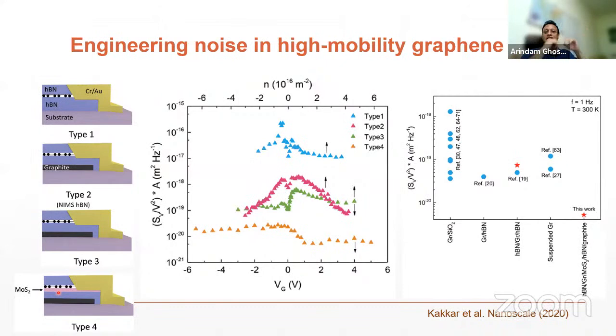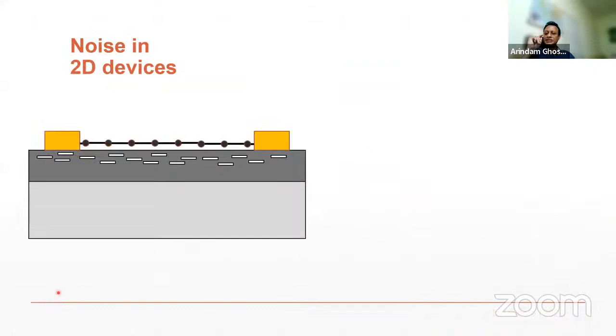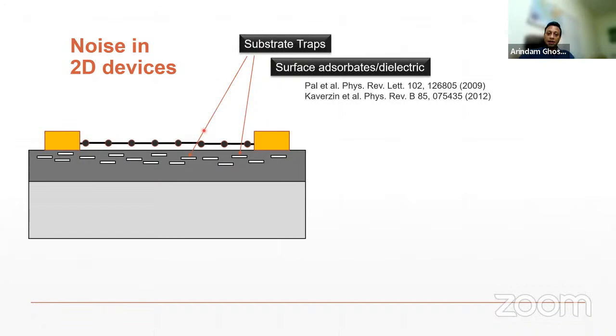Okay. So if you're now asking me, okay, that's all very nice, so where are we with this? Let me just summarize it. So we now know the noise in two-dimensional devices can come from multiple sources. We have substrate traps and we have surface adsorbates. So whenever you make such devices, you always have some material sitting on top of the surface of the two-dimensional material, and that can lead to additional noise and additional traps.